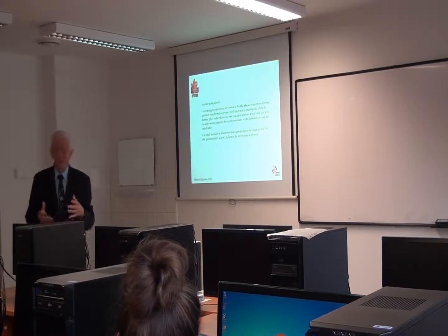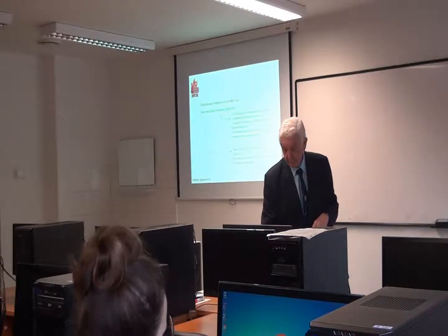If you made all the preliminary treatments according to the rule, and we will see what the rule is, then you have no deformation. All the deformation is only a very slight increase of a couple of microns due to the formation of the compound layer. Practically, as there is no transformation, we have practically no deformation.